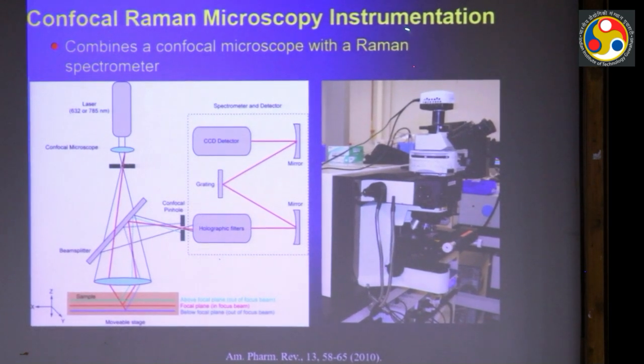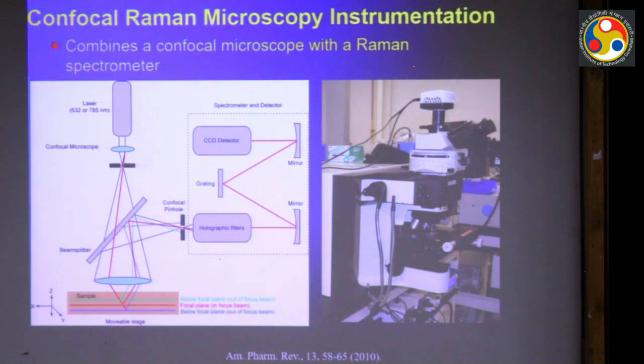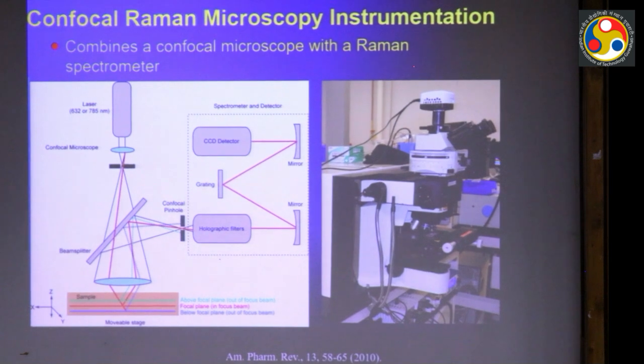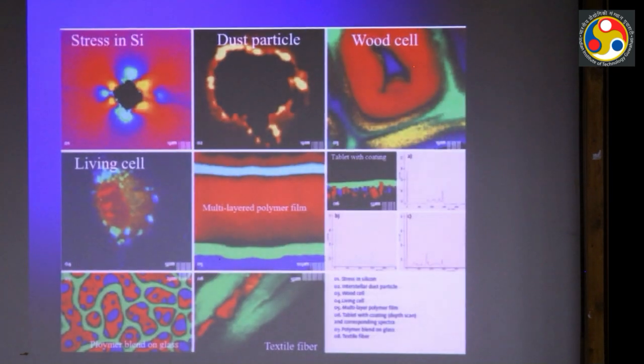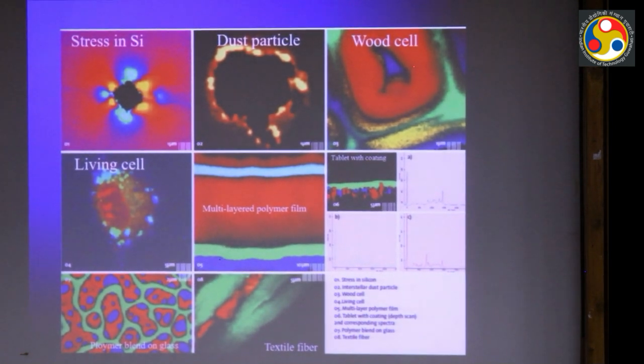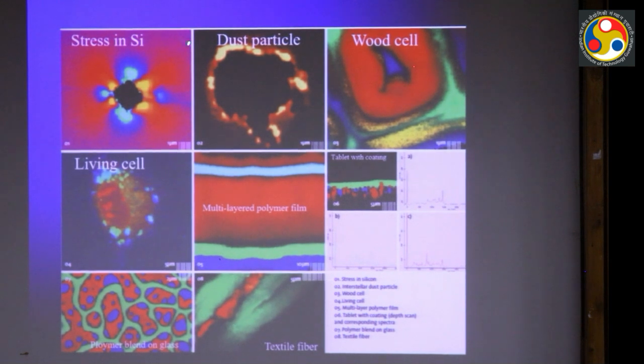We have a confocal microscope, but that is working in the fluorescence mode, not in the Raman mode. So you can actually detect stress in silicon like this one. You see different kinds of contrast around this. This is a silicon wafer and there is some damage here. Around the damage you can see contrast, so that shows the stress profile in the substrate. If you have some dust particle, you can also look into these with this kind of contrast.